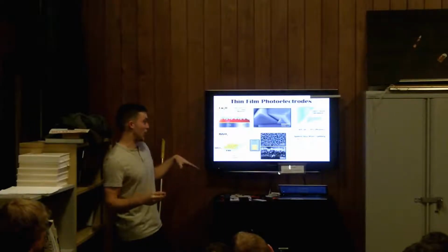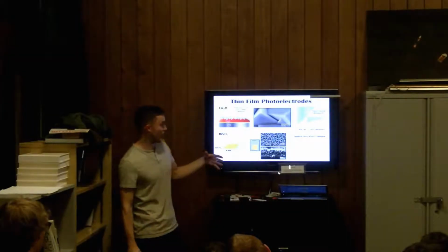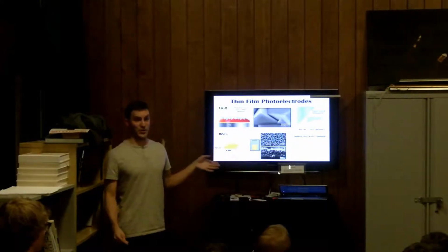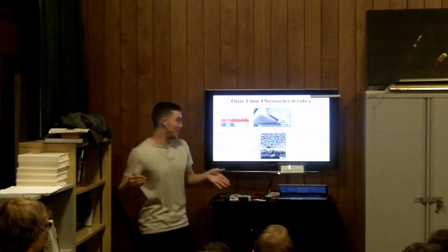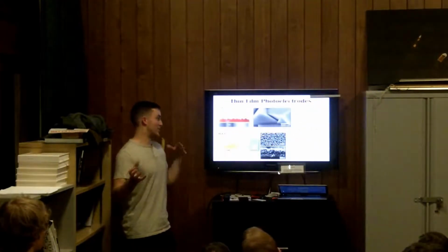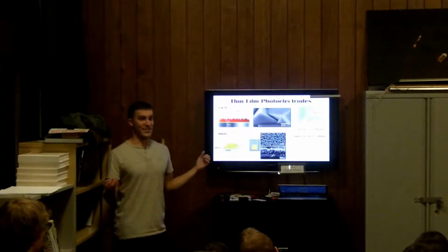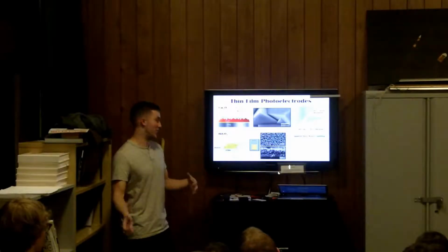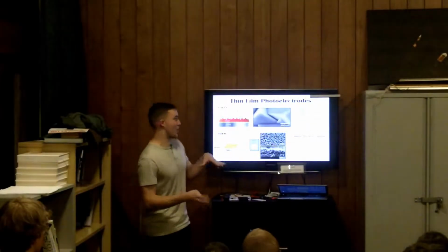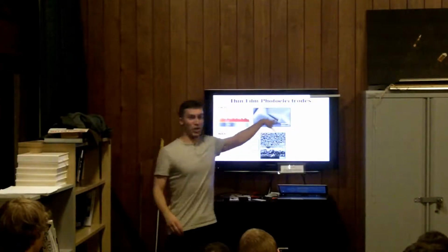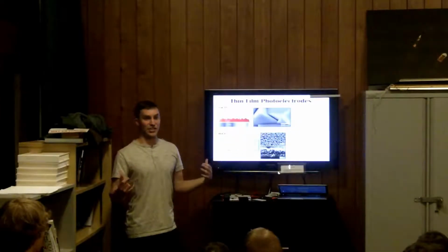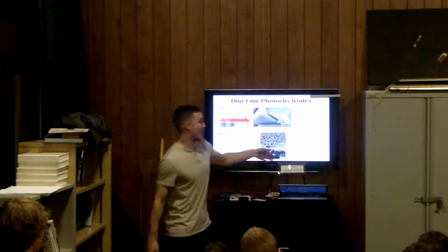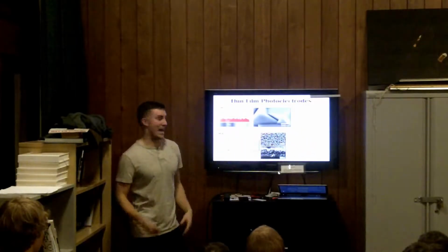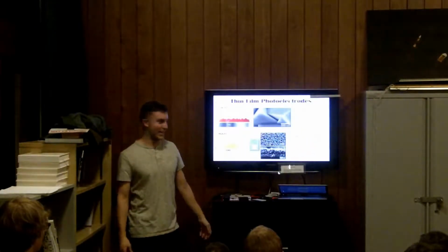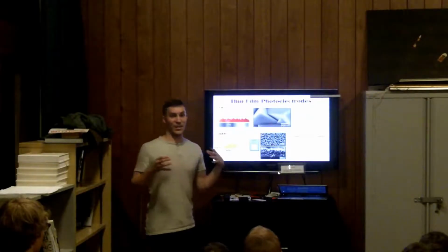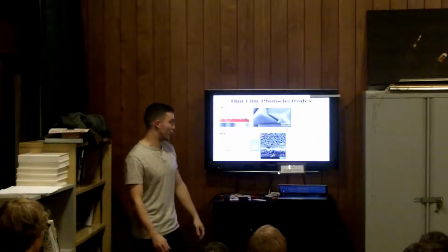This is actually showing you the amount of hydrogen and oxygen that are being produced as a function of time. And they actually have to separately trap the two gases and quantify how much of each they have. But this is nice because we're not just relying upon the currents that we see to show us how much energy we're storing. We know exactly how much energy we're storing by how many hydrogen molecules we formed, right? So this gives you direct evidence that you are storing your energy as solar fuels.